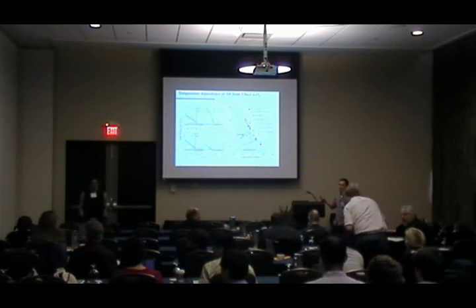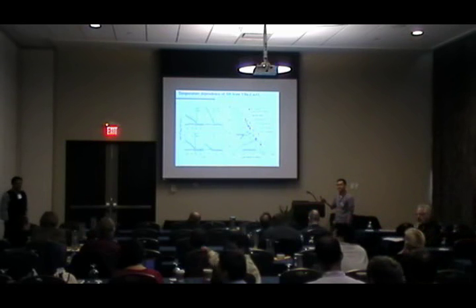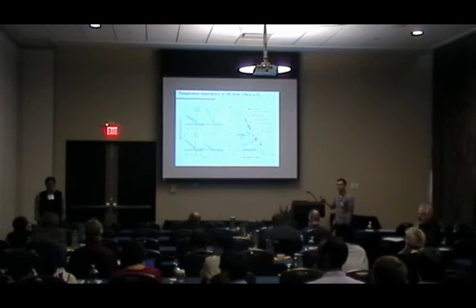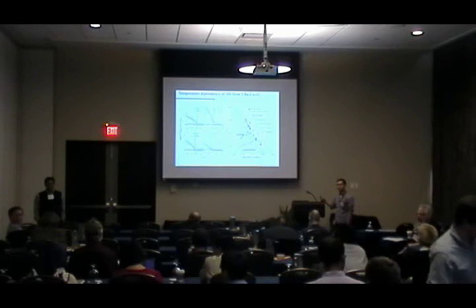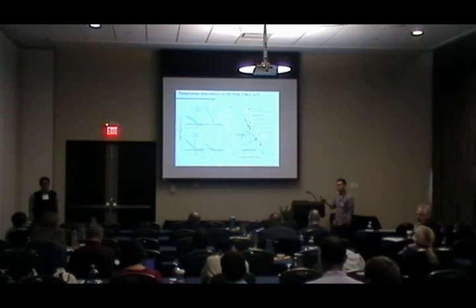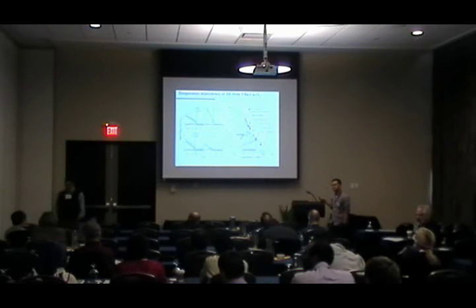Sure. I have an old story to remember. In the very early days of cuprates, where the samples were not single crystals, but very highly pure and uniform polycrystalline samples, in the early days of pseudogap, before we knew it was a pseudogap, there were distinct anomalies in sound propagation characteristics. In some shear mode, there was a Pippard anomaly. In the damping, there was something like a gap opening. In many transport measurements, like conductivity, if you measure d/dT of log rho, you will see some anomaly. These were subtle. And at the time, it seemed, I can give you the references, that these were indicative of a clear phase transition. And if you looked at high quality crystallographic data, apical oxygen position seemed to move.